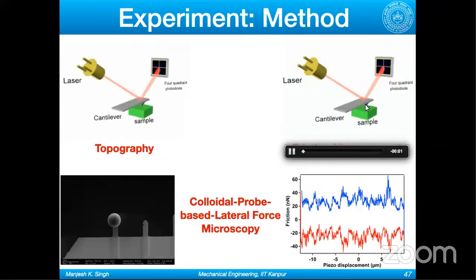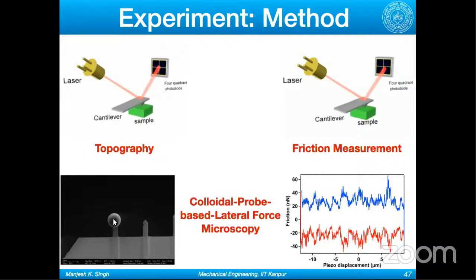So we bought tipless cantilevers. We attached silica colloidal spheres on these tipless cantilevers. What it does is that now we don't have a very sharp tip, and we have a well-defined geometry. We have a sphere, so we have a well-defined geometry. We have a higher contact area because we are using a sphere, so the contact pressure goes down. It will also help us if we want to deduce the contact pressure or contact mechanics, because you have a well-controlled geometry, or a geometry which you know.